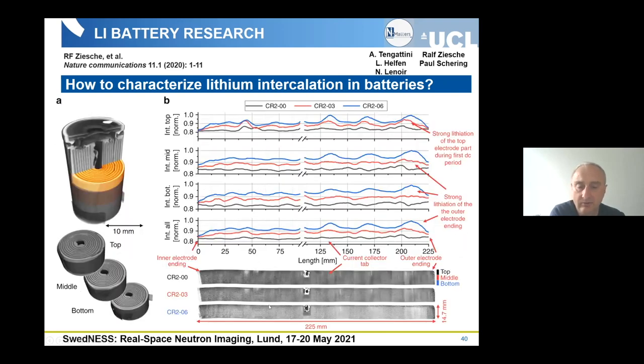Unrolling the electrode, we can see also the lithium intercalation with time. So you can see, starting from the top to the bottom, that we have brighter areas, and these are just the areas where we have more lithium diffusion in the electrode. So this means that combining the X-rays and neutrons, we can investigate such complex systems.